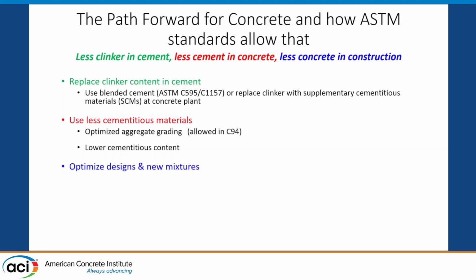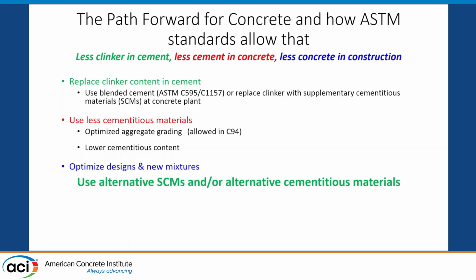So we can replace clinker with content of cement using blended cements according to the ASTM standards, and we can use less cementitious materials. Optimized aggregate gradations are something that is not done very well in North America for the most part. It's allowed in the C94 concrete spec, but not many companies take advantage of it except for the pavers. And we can optimize designs and use new mixtures. And as Mary talked about, there are new alternative SCMs on the market coming out or being developed, and alternative cementitious materials. And there's specification development taking place, but there's a lot more to do.